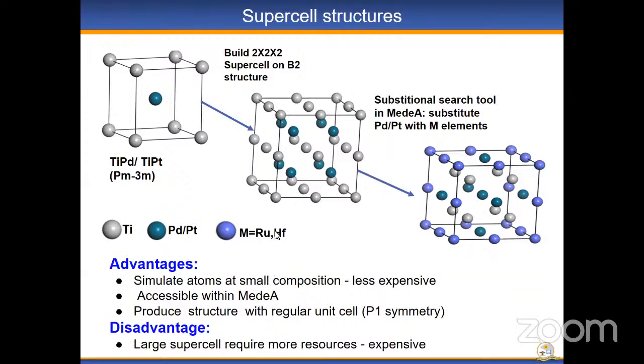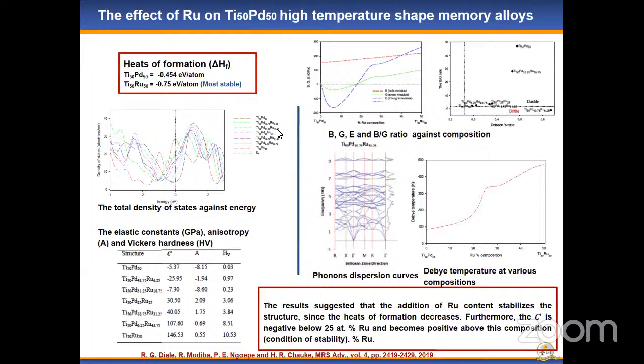And then the few things that we have done here is just to show you that we can still do the same relation where we look at the densities of states, we look at the heats of formations, and we also look at the mechanical properties and look at the strength of materials. As I've indicated, when we are designing this, we were mainly interested to see how ductile the material is, how brittle the material is. So with this approach, you are able to do different kinds of compositions and then check whether these compositions are stable or are ductile or are brittle.